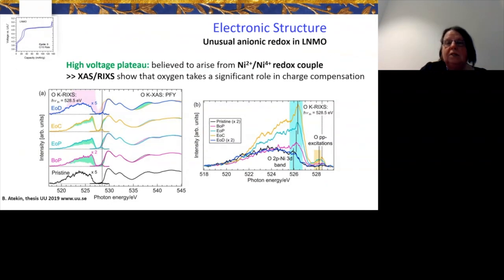knowing that we have this very disordered structure with some kind of redox chemistry to do the electrochemistry of this compound. And to our interest, we could find that we cannot only explain this high potential by being a nickel 2 plus and nickel 4 plus redox couple. We have to use RIXS and absorption spectroscopy to show that oxygen takes a significant role in the charge compensation. So this RIXS data that was taken by Laurent Duda's group in Uppsala, who is in the group that is building the VERITAS beamline at MAX IV, was very instrumental for explaining what's going on.